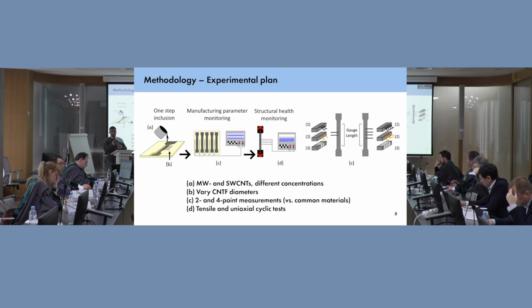And during this process, because we wanted dual-stage monitoring, we insert our carbon nanotube fibers into the gauge length of our material. And we do this so that we can monitor manufacturing parameters, understand if we can see any of the parameters that we want to see during the manufacturing process, leave them embedded here, and use them under mechanically applied load to see, okay, can we monitor how this material is behaving or changing when it's under loading?